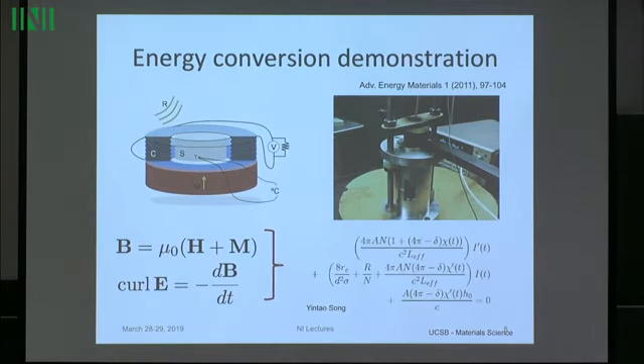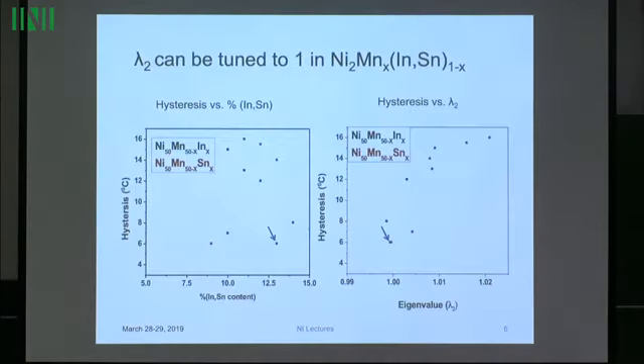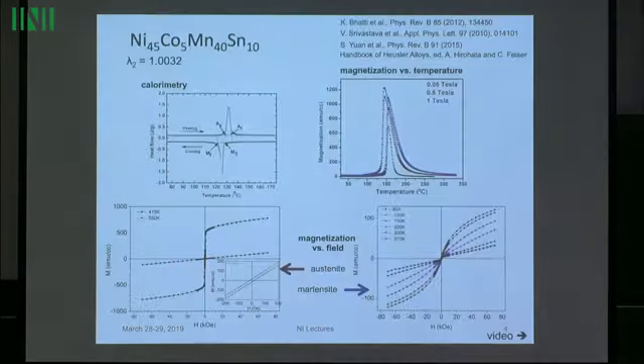So what you should do is take a piece of nickel cobalt manganese tin and put it on top of a permanent magnet. This permanent magnet doesn't have to be a very strong magnet, but the role of the permanent magnet is, as I was showing before, this material is quite soft. So if left alone to itself, it will just demagnetize itself. The magnetic domains will form, they'll all cancel each other out. It won't have any strong ferromagnetism. It's a soft magnet, as indicated by this graph.